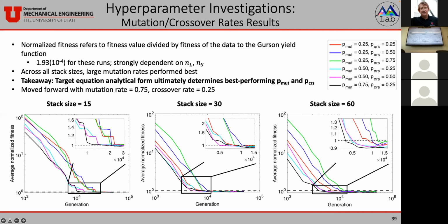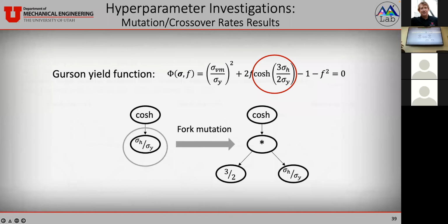What we see from these figures is that large mutation rates perform best. The largest mutation rate, 0.75, is noted with the black line. In these figures, it's at the bottom of the curves. So we see that it's reaching better normalized fitness in fewer generations than other combinations. The reason for this is that the functional form of the yield function requires fork mutation to evolve. Say you have a cosh of some parameter. This requires fork mutation, which takes this parameter and inserts a mathematical operator relating two parameters. In this way, you're able to evolve that cosh of 3/2 normalized hydrostatic stress.